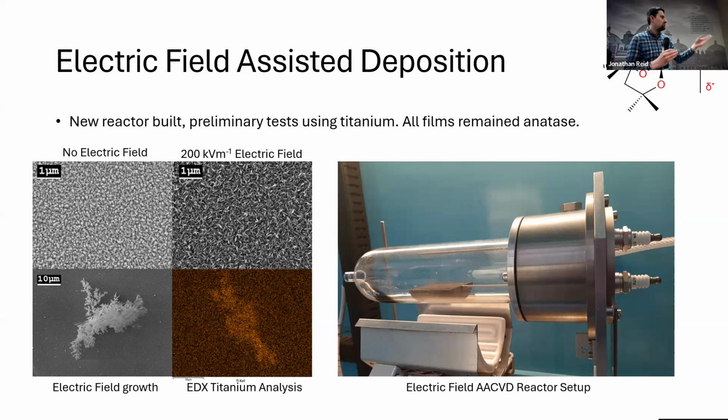An interesting thing that they do, which I wasn't observing before, was growing these dendritic macro structures. You can see this is now on a 10 micron plus scale. Some of them can be observed with the naked eye. They grow out of the substrate material and try to stretch towards the other electrode. When the electric field is turned off, these do actually collapse and fall back onto the thin film material.